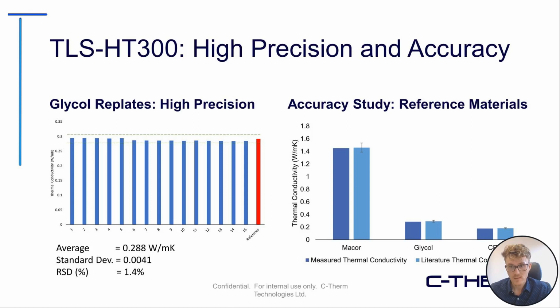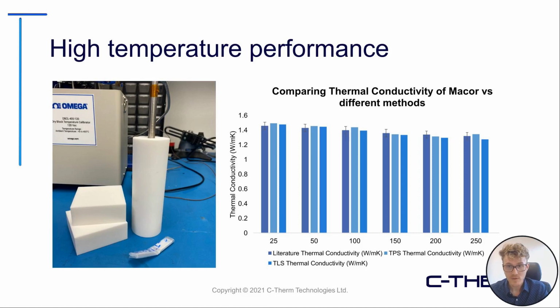Additionally, using some reference standards, including a PMMA core, glycol and Macor, we're able to achieve very accurate measurements of these thermal conductivities as compared to literature value. Now, extending this to high temperature measurement, you can use these Macor cores to do high temperature measurements of the sample for reference. And that's what we did here in this experimentation, where we looked at the literature value of Macor as compared to the reference value found from TLS HT300 and a different methodology, TPS, thermal conductivity measurements, as available on Trident. You can see that all three of these measurements at various temperatures from 25 up to 250 degrees Celsius are all consistently within 5% of the literature value, showing a very accurate method for measuring this.